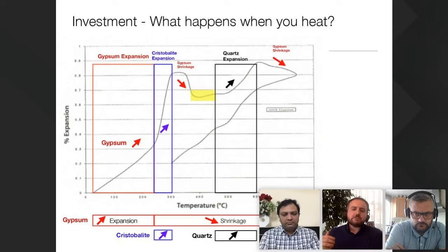There are actually different expansion and shrinkage areas, which is very important and very interesting. First, the first phase between, let's say, 45-50 degrees up to 250 degrees. These are all in Celsius, so if there are US attendees, they can convert it to Fahrenheit. Basically you have this first stage where the gypsum is expanding.